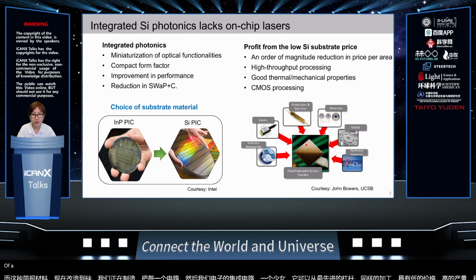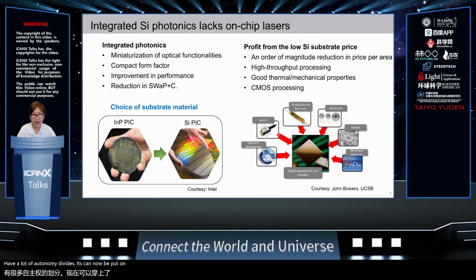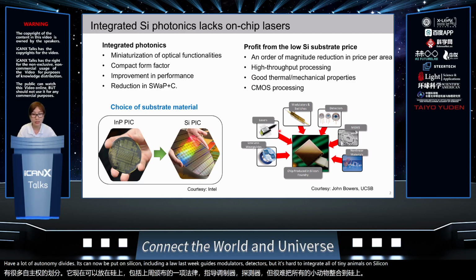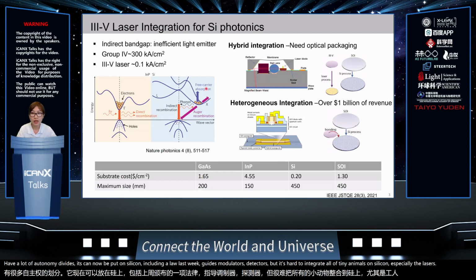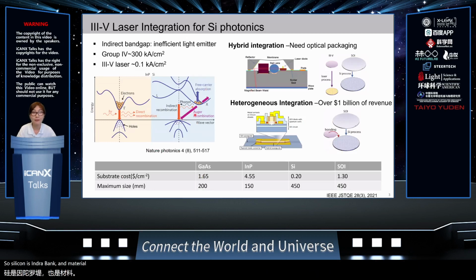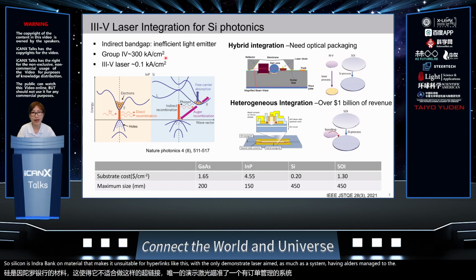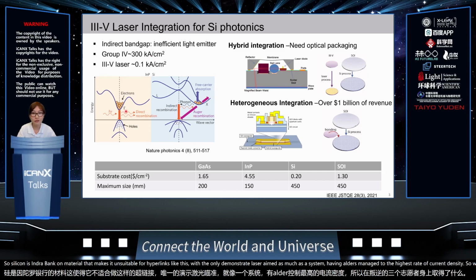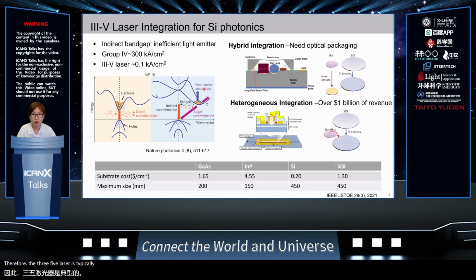A variety of photonic devices can now be put on silicon, including low-loss waveguides, modulators, and detectors, but it's hard to integrate all the photonic elements on silicon, especially the lasers. Silicon is an indirect bandgap material that makes it unsuitable for high-performance lasers, with the only demonstrated laser in this material system having orders of magnitude higher threshold current density than what is achieved in direct bandgap III-V materials. Therefore, the III-V laser is typically off-chip, where optical packaging with optical alignment occupies over 90% of the total cost.